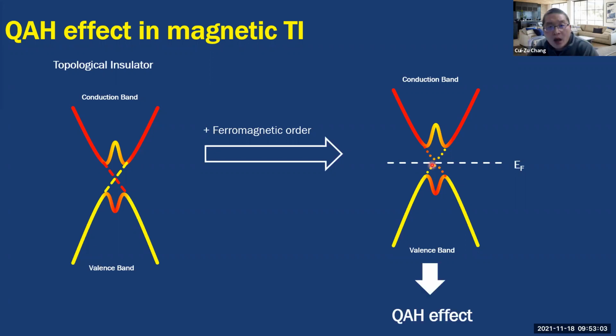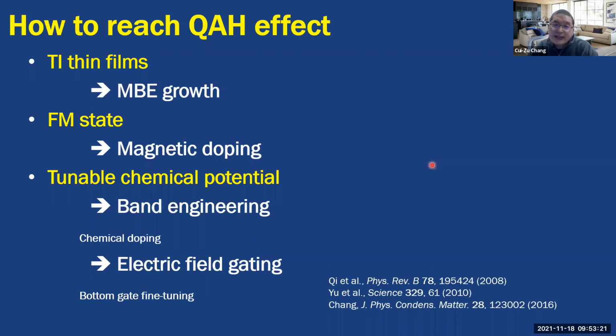This is a very simple picture to understand why we choose the topological insulator for the realization of the quantum anomalous Hall effect, and how to use the topological insulator to realize the quantum anomalous Hall insulator. That is just a theoretical picture. As an experimentalist, we need to convert the theoretical picture into experimental steps and procedures. There are 3 steps. The first step is that we need a high quality topological insulator thin film. Our approach is MBE growth. I'm an MBE grower. The second is that we need to introduce ferromagnetic properties into the topological insulator thin film.